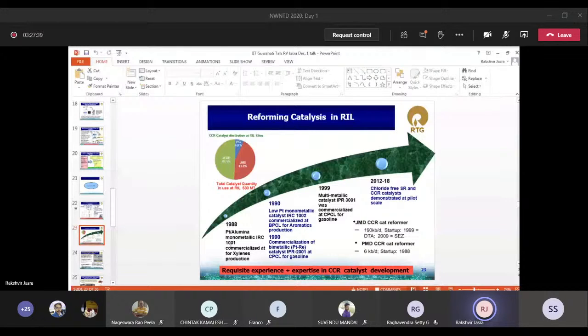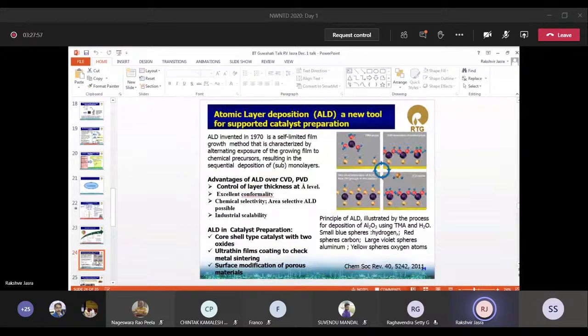Here we have really used our understanding and knowledge of nanoscience. What we did, we said we will not put any chloride, but we will put some oxide layer on platinum and tin after loading on alumina, and that should be acidic, and also that layer should be only a few nanometer thick layer of that metal oxide which has acidity. So acidity will come from that, and when that nanometer thick sheet is put on platinum and tin over our first initial catalyst, then it helps.